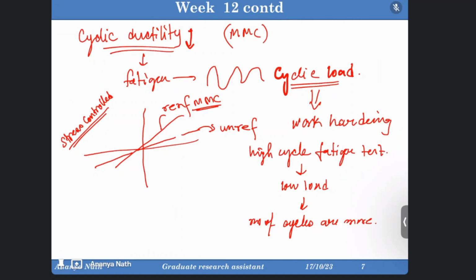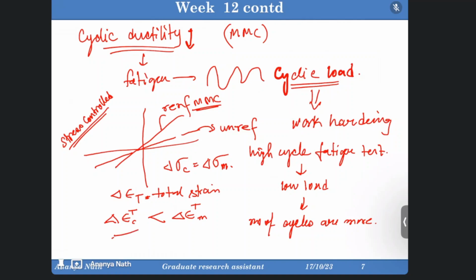In case of strain control or low cycle fatigue test, it's often found that the fatigue life of reinforced metal matrix composites is lesser than the unreinforced. But before that, if I talk about the stress control, whatever stress I have applied to the composite will be the same as whatever stress I have applied to the metal. So if this is the total strain, then the total strain of the composite will be lesser than the total strain in the metal. And as a result, if strain is less, it will take longer time to fail. So this is how the fatigue life is more, and it's proved in case of MMC.